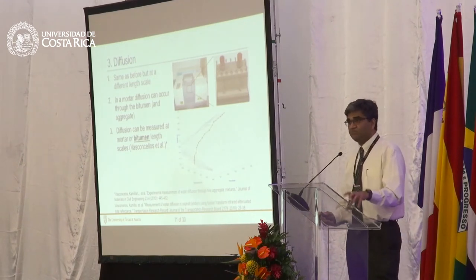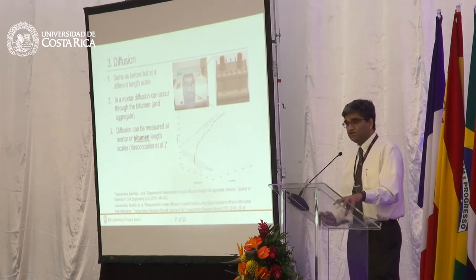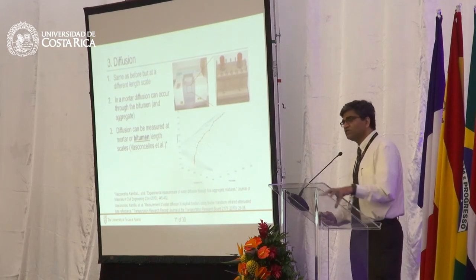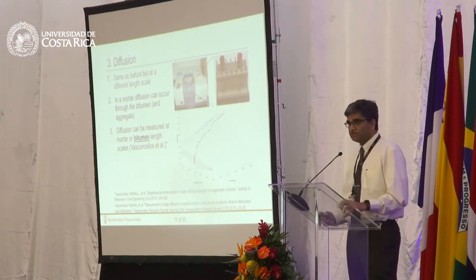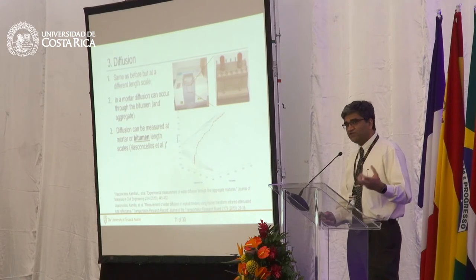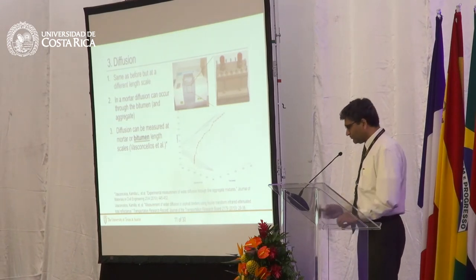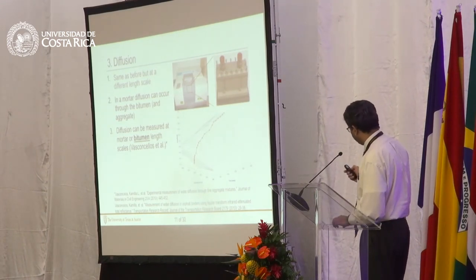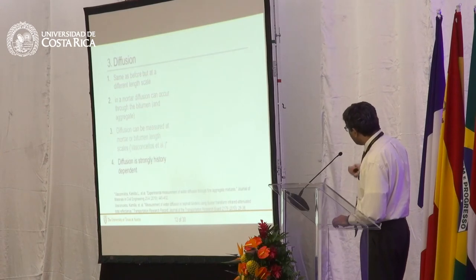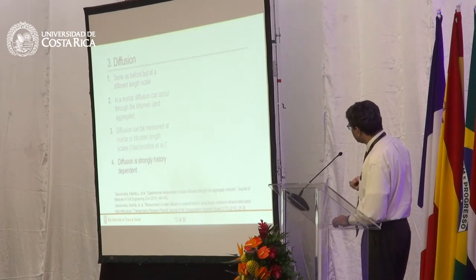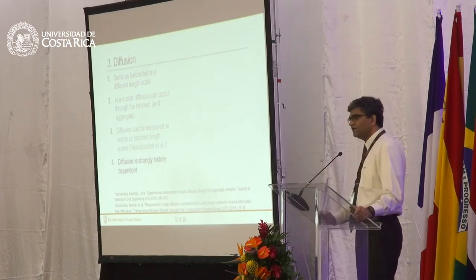And what we've seen is the diffusivity of binder, or different kinds of bitumen that come from different sources, is vastly different. So the inherent ability of each binder to allow water to flow through it is very different. The last part of this diffusion story is that we also found the diffusion is strongly history dependent.